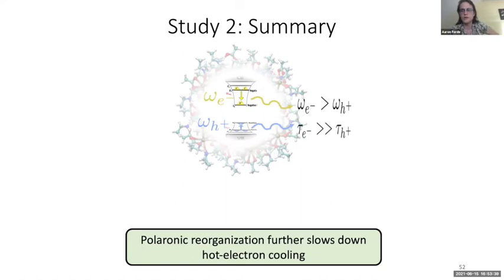So there were ionic modes from the surface which were in resonance with the energy gaps where the luminescence would come from. So it led to much faster non-radiative relaxation than radiative. So those were the two main findings from that work.